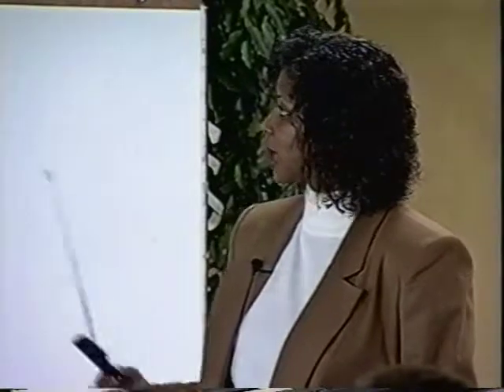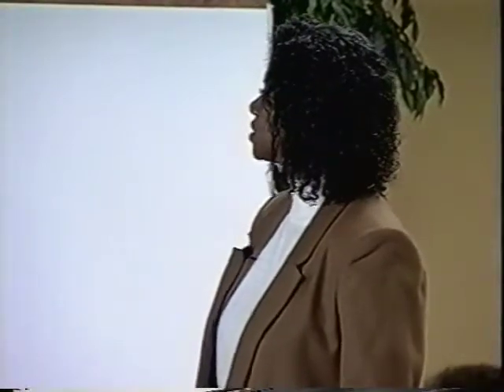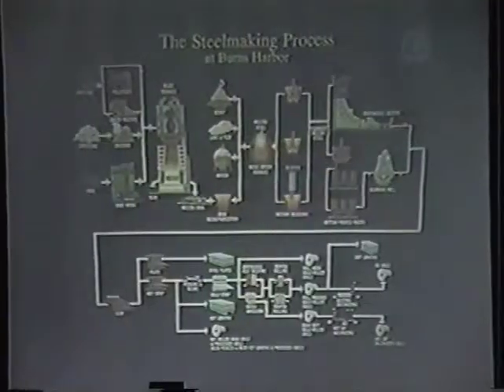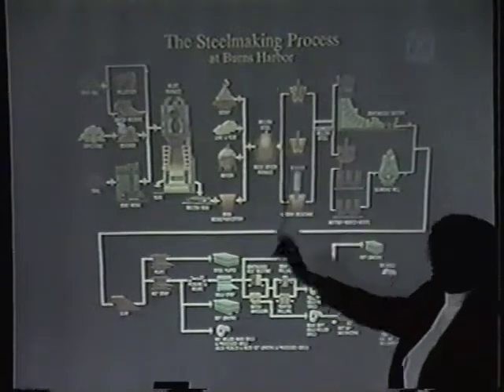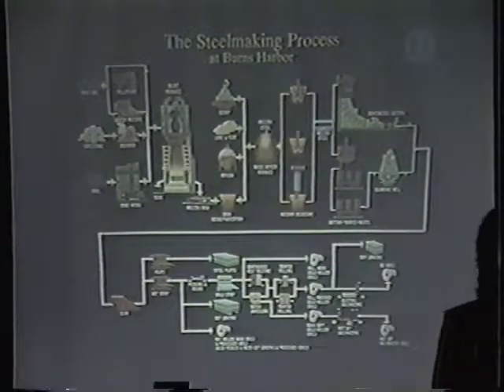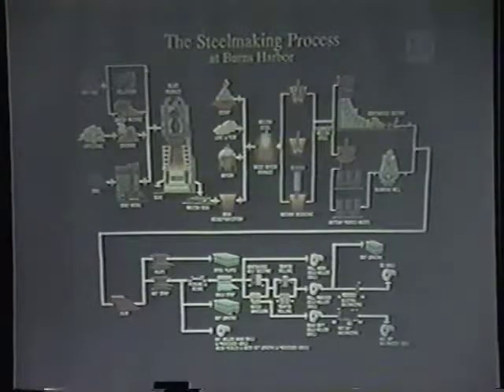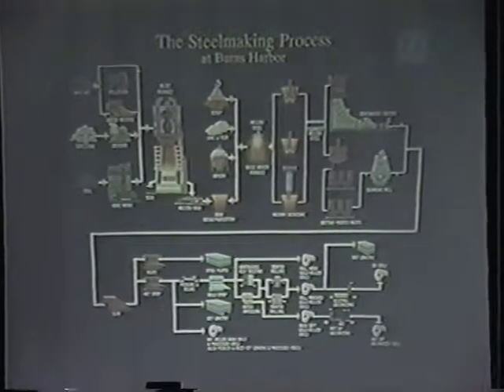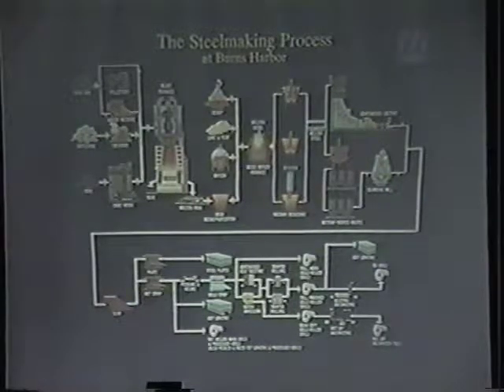And you're going to learn a lot more about pelletizing and limestone going into sinter stone and coal going into coke in our first session this morning. The first step is the blast furnace operation. We're going to charge in the coke, the sinter stone, and the iron ore pellets. And through this blast furnace process, injecting hot air onto the coke, we're going to generate heat and melt down the sinter stone and the iron ore pellets that are in there. It takes about 2 hours. We're going to produce about 600 tons of hot metal iron or liquid iron.